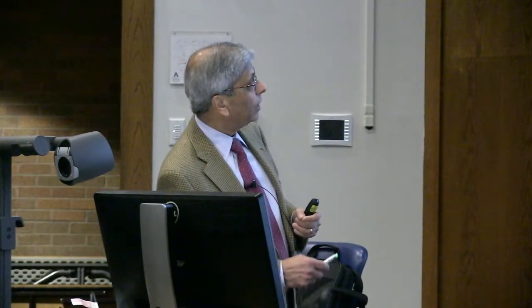And of course, the first reaction is it's not going to work. We can't do it. So, go and do it. So think of just an edge-emitting Fabry-Perot laser, processed just like a laser. Here's the N contact, the P contact on top, and the light coming out from the edge. And of course, we put DBRs, which we do in most lasers anyway. And here's the laser heterostructure, multiple quantum disks. And the P-type, N-type, and so on and so forth. That's the mode profile. It's slightly more leaky than gallium arsenide or indium phosphide-based lasers, but so what? And there you are, beautiful lasers.